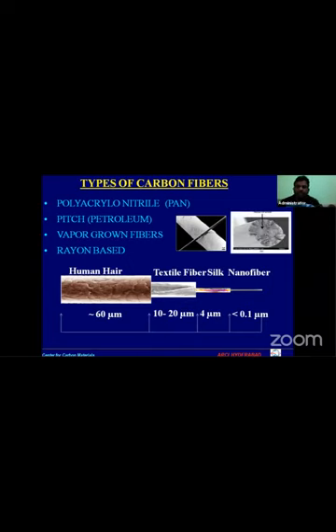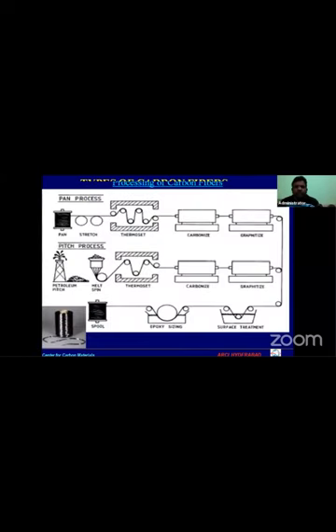This is the different texture of the carbon fiber. Now, how is carbon fiber processed? You start with a polymer fiber in a special furnace. You stretch it, and that is called thermosetting. After stretching, this will become stable. And this stable fiber is carbonized. Carbonized means heat treatment up to 1000 degrees, and then graphitized. This graphitization means heat treatment at more than 2500 degrees centigrade,